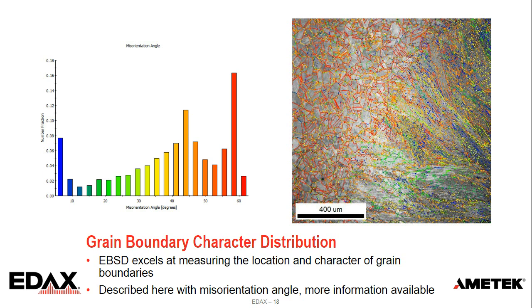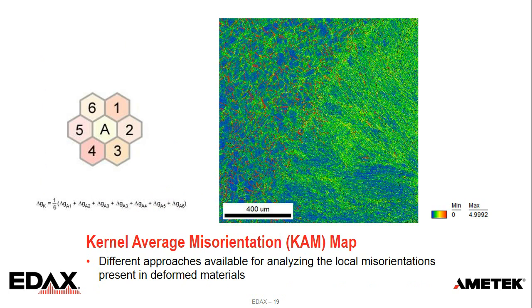We can also measure local misorientations. It's a little tricky how we choose to describe this. Sometimes it's termed strain, or plastic strain. It's really not strain, but that's what it's called. But essentially, as we permanently deform a material, it introduces misorientations. And if these misorientations are large enough to be detected with EBSD, we can count them.